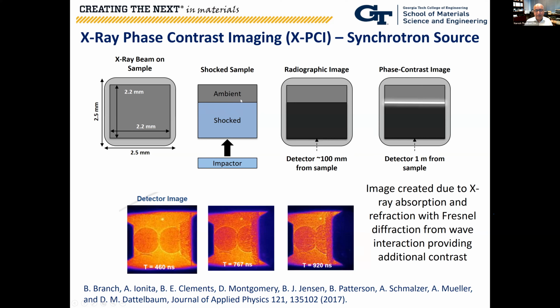Because of that density difference, you can have an X-ray radiographic image that will give you contrast between the high density and low density regions. In an X-ray radiography setup, the detector is placed fairly closely to the sample being imaged. However, in phase contrast imaging, the detector is further away, so the image created is due to X-ray absorption and refraction, as well as the Fresnel diffraction that comes from the interaction of that wave as it propagates through the material, producing additional contrast. So unlike X-ray radiographic imaging, you have significantly better contrast between different density regions.